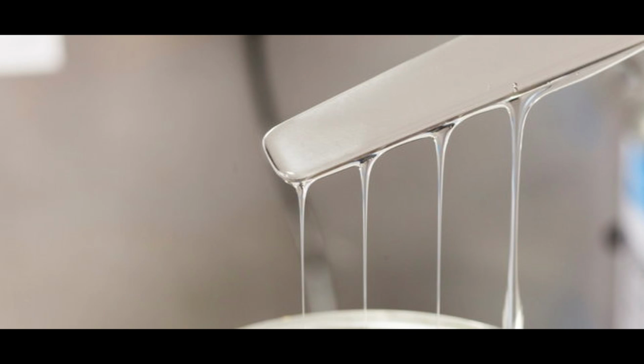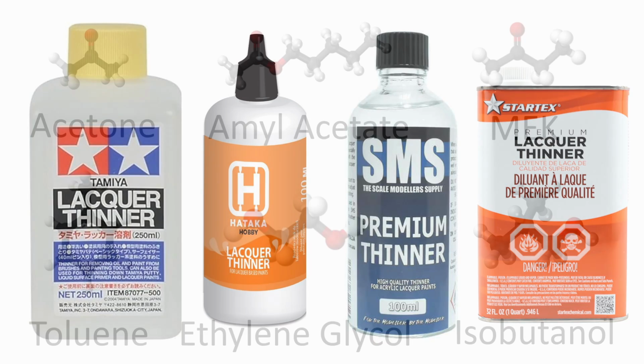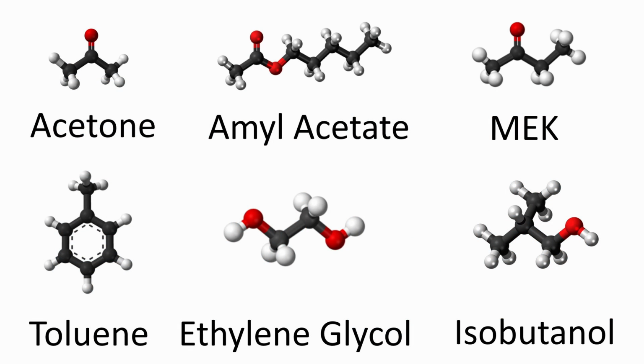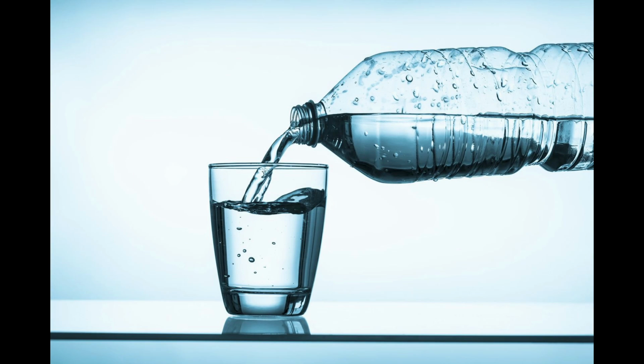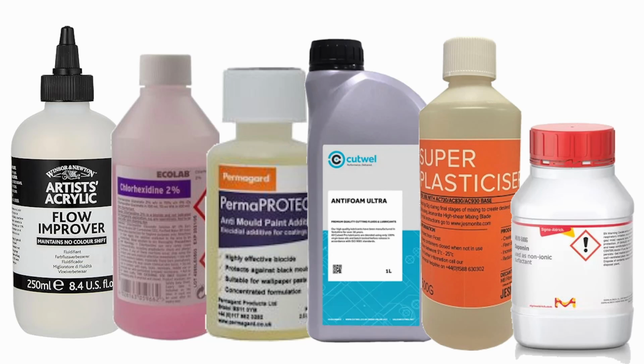Choosing a more native acrylic polymer allows the use of more traditional organic solvents that provide good wetting and spraying characteristics, allow generally simpler formulations, but come with various unpleasant issues primarily from their VOCs. Use of an acrylic emulsion, on the other hand, allows the use of water as a solvent, but also generally more complex formulations to deal with the peculiarities that water brings from a physical and chemical point of view.